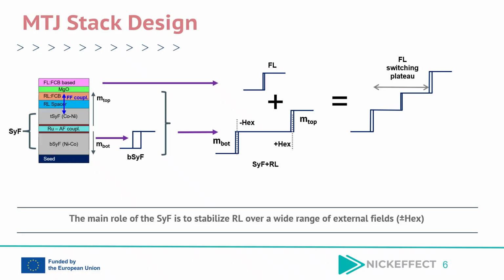To achieve optimal switching behavior, the SyF is further optimized through the adjustment of cobalt and nickel layer thicknesses, the RKKY coupling strengths mediated by the ruthenium spacer, as well as the RL spacer thickness, which strongly influences the switching stability of the reference layer. The MgO-based tunnel barrier separates the reference layer from the free layer, FL, enabling spin-dependent tunneling and high TMR ratio.